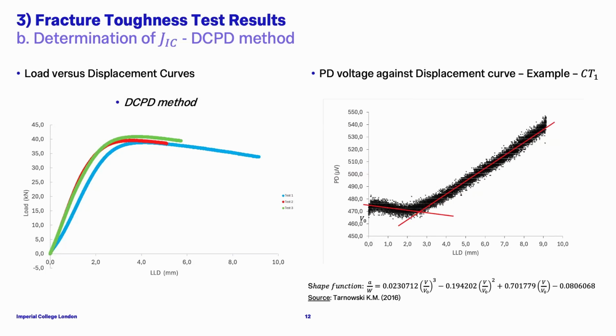So here are the load versus displacement curves. They're all quite the same shape. And on the right-hand side, there's the PD voltage against displacement, where we can find our V0 value. According to the standard, this value is when the crack initiates. And instead of using the shape function mentioned in ASTM, I used another shape function developed by another former PhD student at Imperial College, which I found to be the best to describe our type of test.